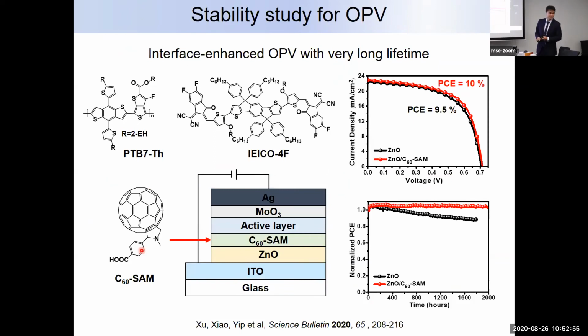The other interface I'm looking at is the electrode and the bulk heterojunction interface. We are using zinc oxide as the bottom electrode, and you know that in organic material, a lot of time it is quite incompatible. Therefore, we introduce this fullerene self-assembled monolayer, trying to covalently bond an organic electroactive molecule to the zinc oxide surface. I think Johnny knows this very well. I think he has a long-time Nature Materials paper talking about self-assembled monolayer modification of the inorganic material.